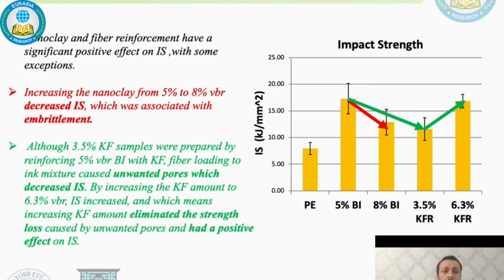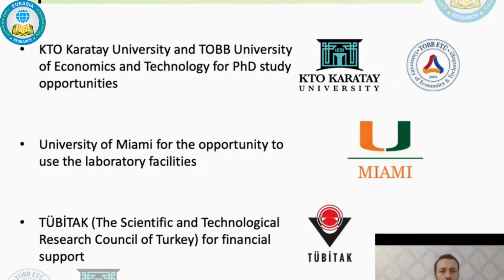But when the Kevlar fiber amount increased to 6.3%, impact strength increased again to the level of the 5% base ink group, which means that by increasing the Kevlar amount to a desired level, it eliminates the strength loss caused by unwanted pores and has a positive effect on impact strength.